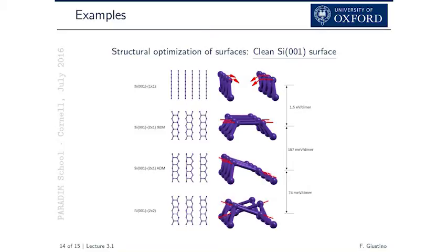So if you do something like that, there are 2 bonds, and basically they flip towards each other. So the one in the middle will form a bonding and anti-bonding combination. The bonding one will be a bit lower, so it can be filled by 2 electrons. There will be 2 sticking out like that. So this is more stable because it's lower energy than that. Now basically there are 2 electrons sticking out like that. If you perturb that slightly, if you break the symmetry, you will see the system, boom, collapses to this one.